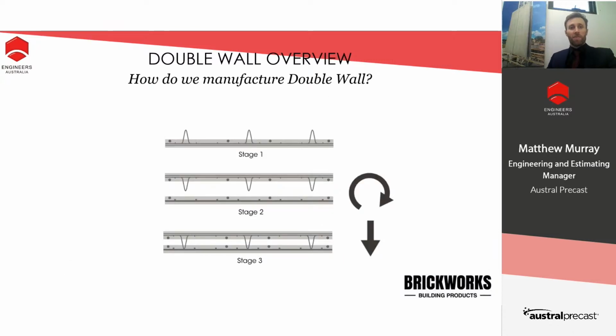So how do we actually manufacture double wall? The manufacturing is predominantly done in 2 stages of each concrete shell with a flipping component in between. So on day 1, we make the first shell of the double wall, which has all the concrete and reinforcement and girders in the first shell. That is then cured overnight to reach a minimum of 20 MPa strength.